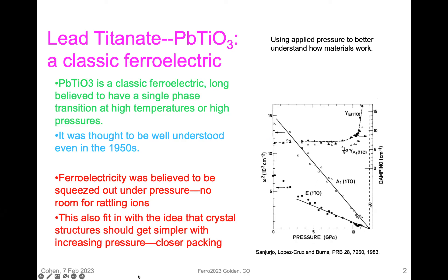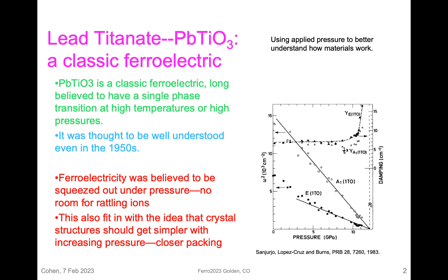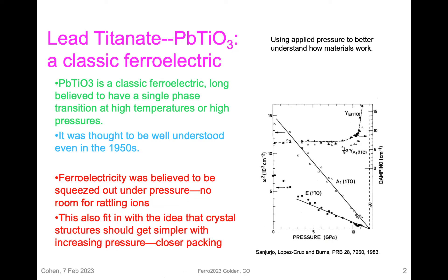This was published in 1983. This is Raman versus pressure, and at 12 GPa, the Raman modes went to zero frequency. Above that, no clear Raman signal was seen, consistent with ferroelectricity going away with pressure. And there was a long-held idea that crystal structures should get simpler as you go up in pressure.